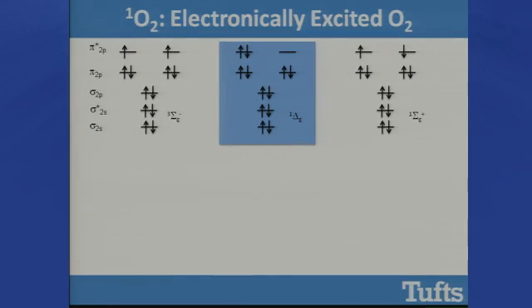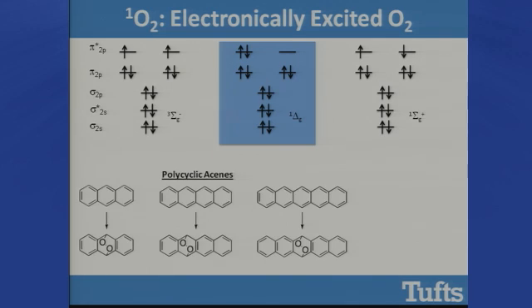Now, as an organic chemist looking at Singlet-Oxygen, why would someone like me be interested in it? Well, from an organic chemistry perspective, Singlet-Oxygen does beautiful organic chemistry. It does things like ene reactions with alkenes, and Diels-Alder-type cycloaddition reactions with these polycyclic acenes, namely anthracene or tetracene or pentacene. And it actually does this reaction in a very clean fashion and does so with pretty impressive rate constants. It turns out that the rate constant between Singlet-Oxygen and pentacene is somewhere around 10 to the 9 inverse molar inverse second. So we're approaching diffusion control here for a very clean reaction.